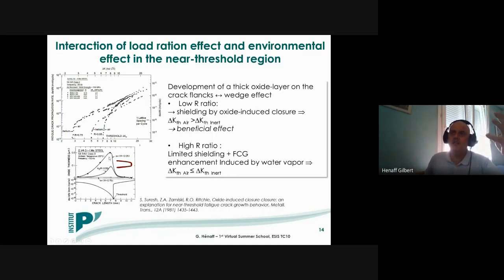And what you can see is that in ambient air near threshold, you have an oxide thickness which is much more important than in other environments, or even in ambient air when considering a higher value of the load ratio. So that means that near threshold, at low R ratio, you have a kind of wedge effect induced by this thick oxide layer, which will in turn induce a shielding of the crack tip and reduce the effective value of the stress intensity factor range at the crack tip. And as a consequence, in most cases, the threshold in air will be higher than the threshold measured in inert environments or environments with only very small traces of water vapor.